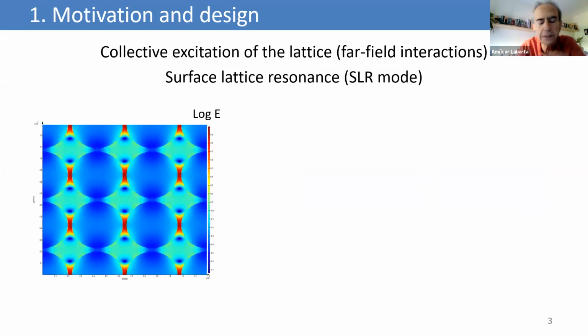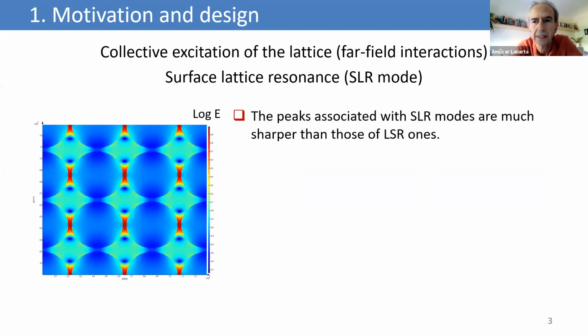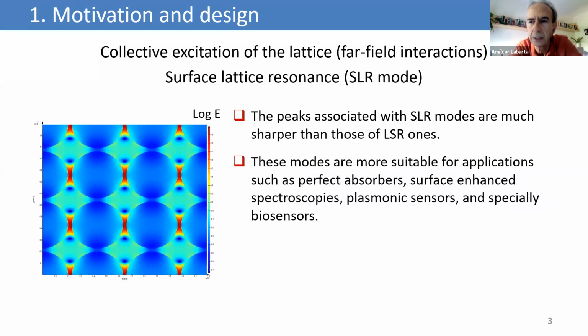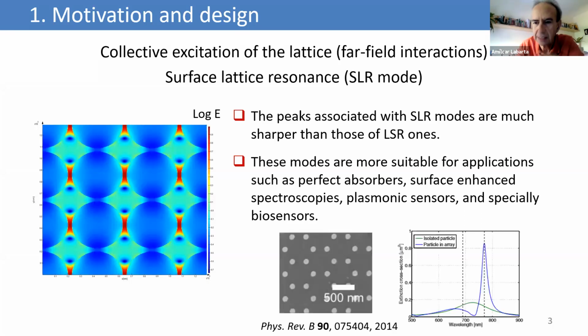But when we have many of these elements arranged in a lattice with translational symmetry, we have additional ways of excitation, a kind of collective excitations, which is just the constructive interference between the excitation of each of the elements in the lattice. In this case, the associated peaks are much narrower, so they are more suitable for applications, if you want a specific wavelength and not a broadband situation, and you want to get high absorption, for instance. Here is an example of one of these excitations in a simple lattice, which is a honeycomb lattice of dots.